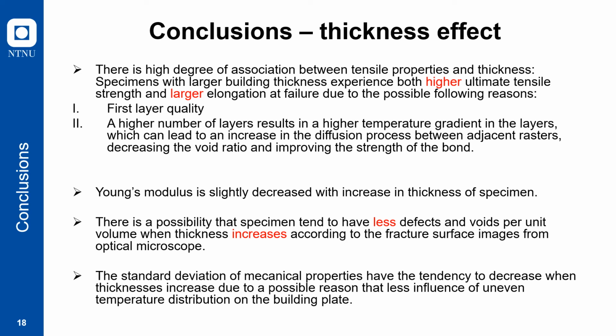And second, as you can see from the table I showed earlier, Young's modulus slightly decreases with the increase of the thickness. And there's a possibility that the specimen tends to have fewer defects and voids per unit volume when thickness increases, according to the image. So for detail, we still need to do the voids and defects analysis of the fracture surface to confirm this hypothesis.